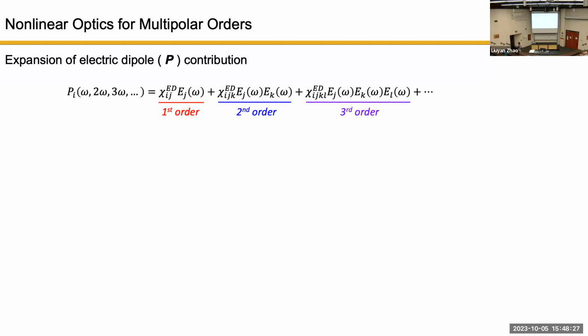But in addition to that, if my field is very strong, this term comes out: I will have two copies of incoming light combined together to form an outgoing light that has a frequency of twice the incoming. That is the so-called second harmonic generation. Omega plus omega equals 2 omega. I require two fields to come in together and generate one field out. That's second order. And on top of that, you can imagine we have third order, fourth order, and so forth. When we look at them, the difference between different orders is really this coefficient that is bridging the incoming field and the outgoing field. The higher the order of the process, the higher the rank of the tensor in front of these fields.